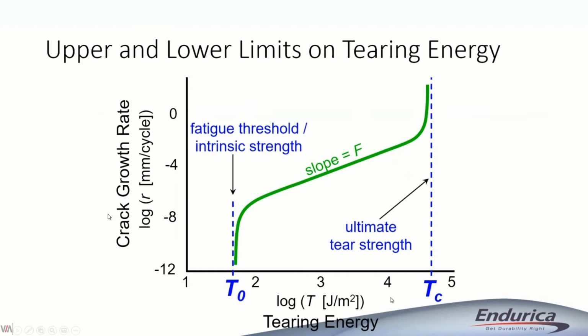The x-axis is what we call the tearing energy. Basically that's a measure of how hard you're pushing the crack, right? So higher loads, higher strains, that's higher tearing energy. Crack growth rate, that's how quickly the crack is developing. The upper limit is what some people call the tear strength or the rupture strength, TC, the critical tearing energy. If your tearing energy exceeds the value of TC, then you have a crack that grows very, very rapidly, so rapidly that it's not a fatigue problem anymore. It's a strength problem.